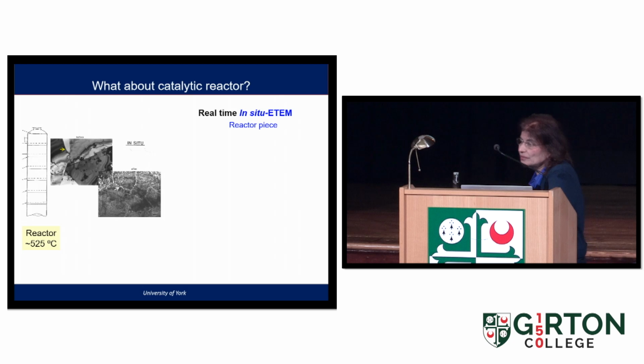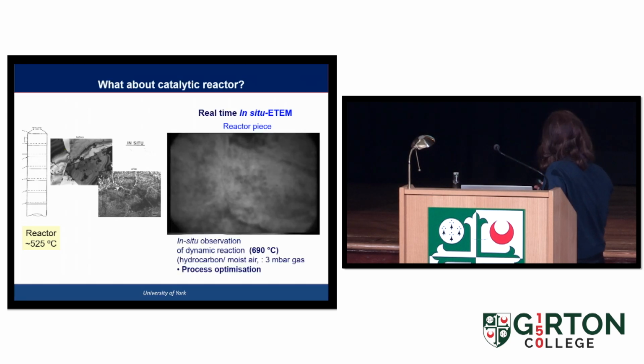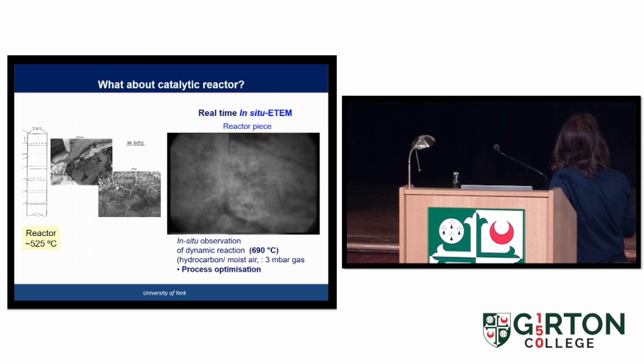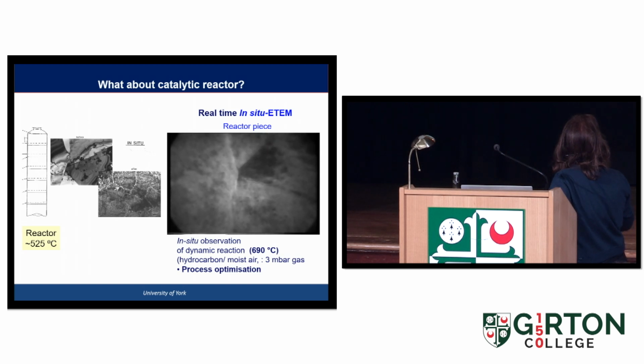Obviously they couldn't destroy these reactors. They said, can your in situ machine do something for us? So we said, okay, we'll try it. We took a little piece from the top here and looked at it in the machine. You can see this is a real-time video. This is the grain boundary, and we put the same environment in our machine, and we begin to see how these grain boundaries then precipitate and crack.